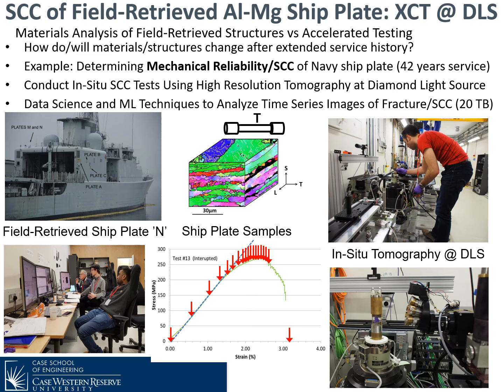So initially, the people on the left bottom are watching the tomograms as they evolve. And we start to decide when we should start taking more pictures. So obviously we take them at the start because we need to characterize the starting material and structure. They're relatively infrequently taken until we start to see activity in the material. And then as you can see by the number of arrows, quite a few tomography scans are taken that are 3D in nature and very dense in terms of their imaging, in that we probably have about 20 terabytes of data even in only 2 tension tests.